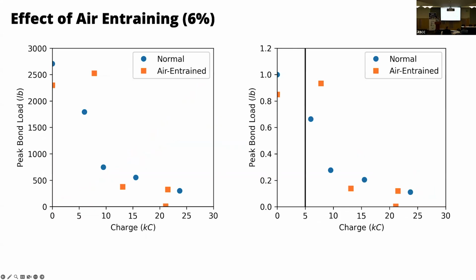As a result, this graph shows the ultimate bond strength of the concrete. For normal concrete, the x-axis is the charge, which means that 0 means no corrosion, and the number is going to be increasing, which means a highly corroded state. So the degree of corrosion is high on the right-hand side. The y-axis is the peak bond strength. For normal strength concrete, as long as there is no corrosion, the highest bond strength is shown. However, as corrosion progresses, the strength goes down. That is just reasonable.